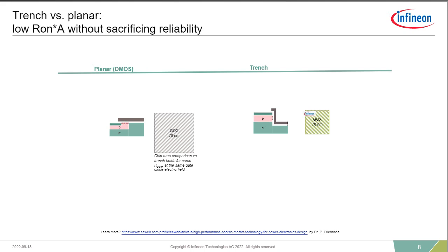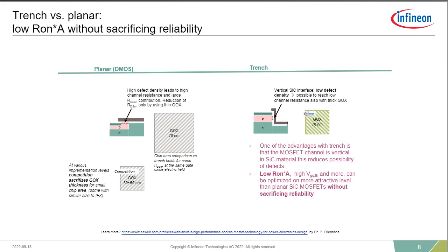The reality is that when comparing the trench base to the DMOS device, if you were to have the same gate oxide thickness, the overall size of the die for a DMOS device would need to be substantially larger in surface area in order to have the same RDS(on) specification for the same gate oxide thickness. And the challenge here is that that's not really happening in the industry. So in order to have devices that have relatively the same area of die size and can be competitive in the mass market, you have to reduce the overall gate oxide thickness of DMOS devices into the range of 30 to 50 nanometers in order to have a competitive die size and be competitive in the marketplace.